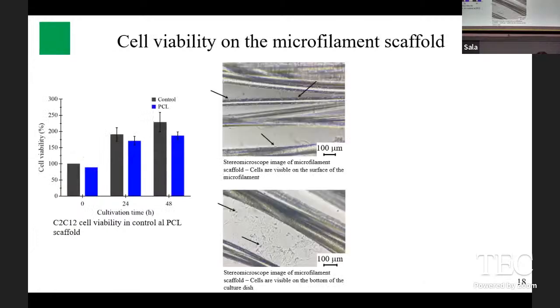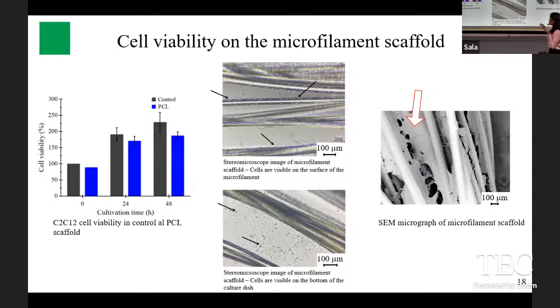And also for the cell viability of the microfilament scaffolds, we measured the amount of cells through time, and we saw that they increased, so the scaffold was not toxic. Here in the middle, I wanted to show you two images, one where the cells were properly attached on the surface of the microfilament, and one where the cells fell down. So this is a result that we don't want, but however, we were able to achieve the good result. And this one over here on your far right was a filament that we left for 15 days to grow with cells. And as you can see, cells started to mix between each other and making this tissue between the filaments.